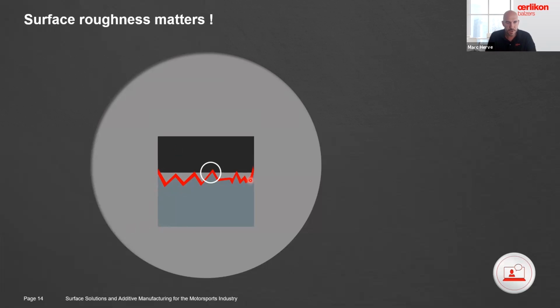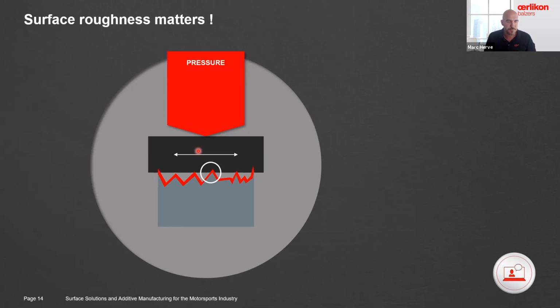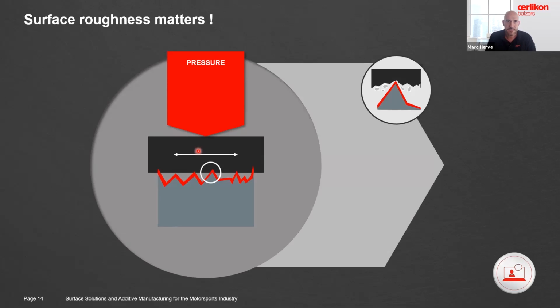So if we come back to our tribo system, two components, you start applying pressure and a little bit of movement. Many things can go wrong when you get your coated parts. One possibility is that the coating, being so hard on the rough surface, is abrasive for the counterpart. On one hand everybody is happy, the coated part gets no more wear, but for the whole system, you still have wear. No good. Another possibility is that the counterpart is hard enough that we start breaking the peaks of the roughness, and suddenly you have micro coated particles in your third body, and suddenly you have wear because it's very abrasive.